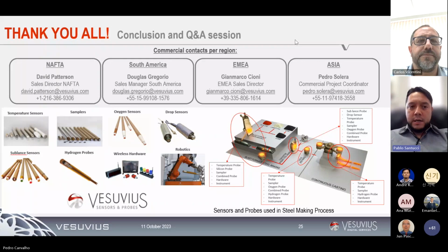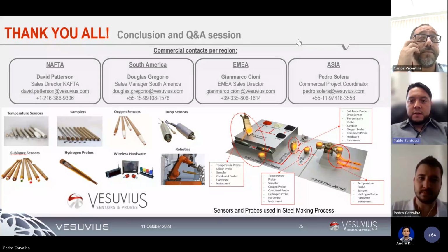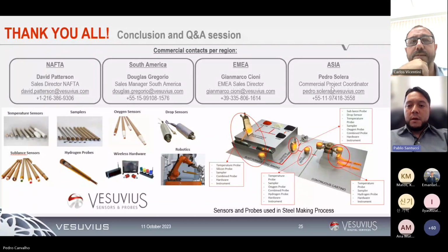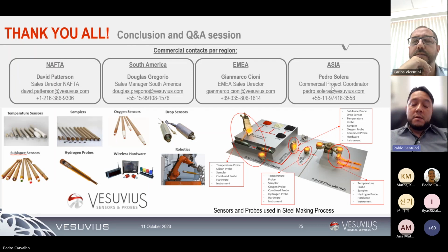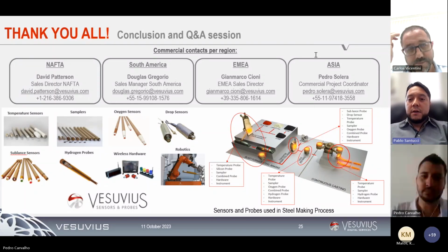Yeah, and just to add some more comments on that question, the minimum purity recommended from the Vesuvius side is 99.97% dry and clean source of nitrogen. So as long as the customer can guarantee that their nitrogen line installation meets those requirements, I don't see any major risk, but bottles are always more, I would say, guaranteed in that regard because it's a sealed container, and certified.